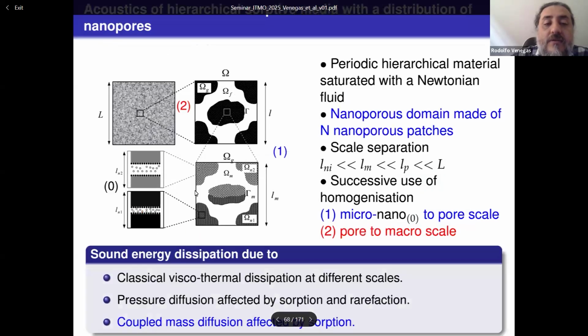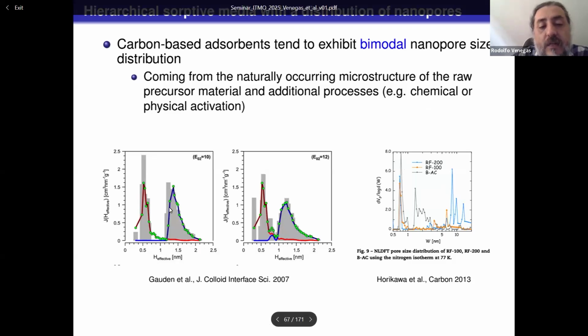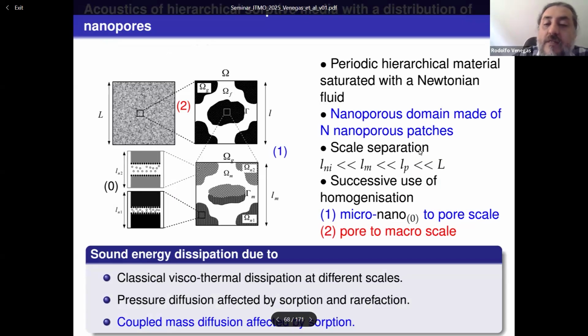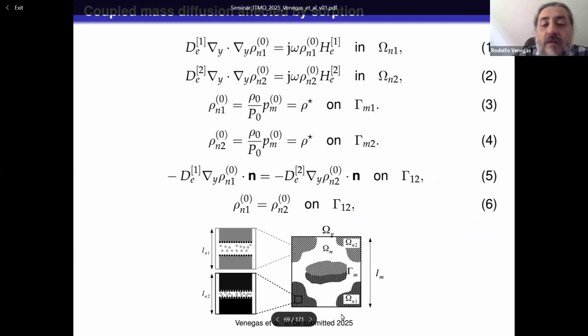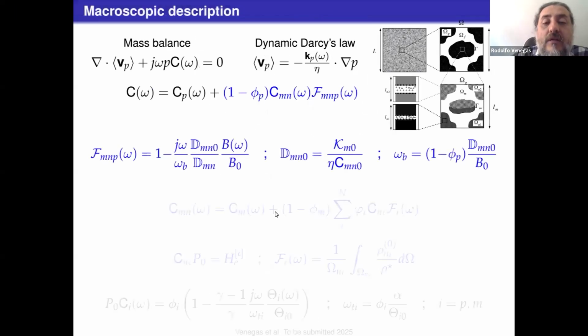So the idea is to consider 2 types of nanoporous patches with different types of nanopores, let's say one with larger nanopores and the other with smaller nanopores, just like we're considering here, smaller nanopores, larger nanopores, in blue here and blue there, so it's about 1 nanometer and 10 nanometers. And we applied the same methodology. The difference is that here we end up with a coupled mass diffusion problem affected by sorption, and this is the coupled mass diffusion problem. So this is formulated in one of the nanoporous patches. This is formulated in another one. On the boundaries that are, let's say, in contact with the surrounding fluid, we formulate this forcing condition here of a constant density forcing this local density field. And in the interface between these patches, we have continuity of mass flux and continuity of density. So the general model is very similar.